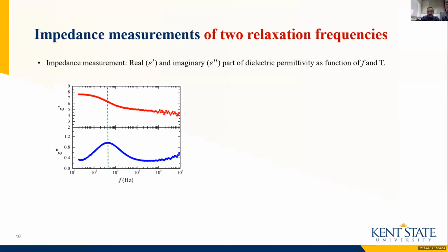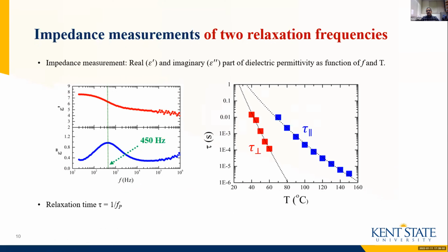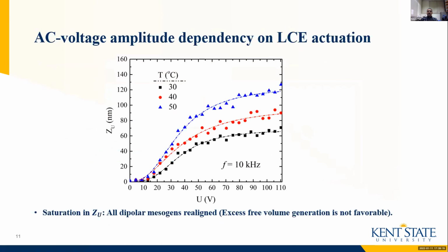So tau perpendicular is less than tau parallel, because a smaller moment of inertia is involved. We did frequency dependent studies using impedance measurement as a function of frequency and temperature. We saw the presence of two relaxation times, tau perpendicular and tau parallel. We associate the low frequency peaks in the frequency response with tau parallel and the high frequency response with tau perpendicular. In the field dependence, we see that with increase of field, the response goes up and saturates. The saturation can be explained by dipolar mesogen realignment with the field. All mesogens realign with the field, and excess free volume generation is not possible.